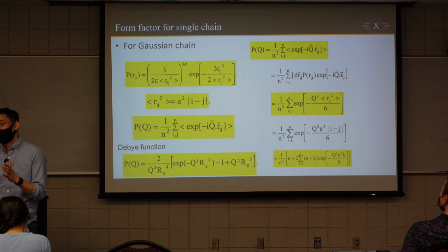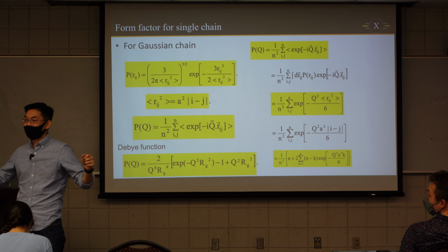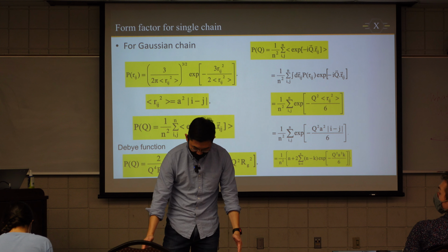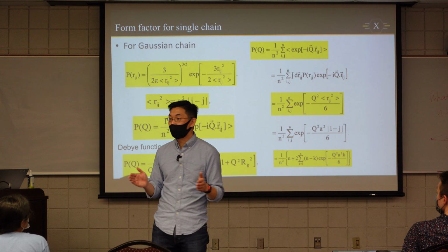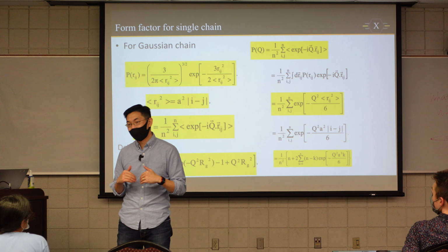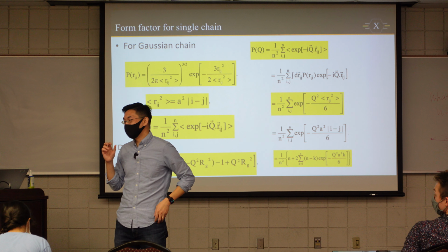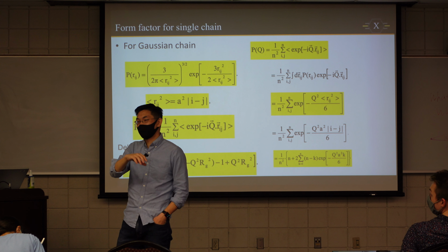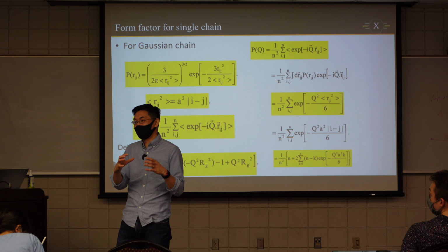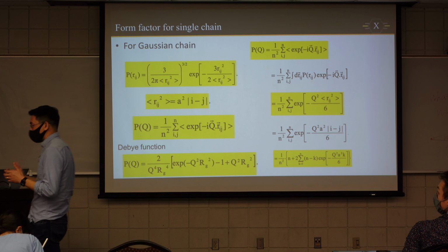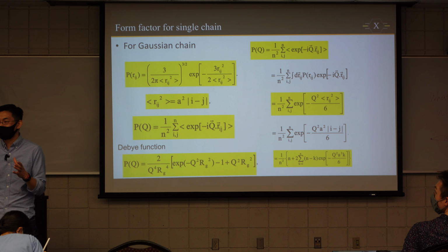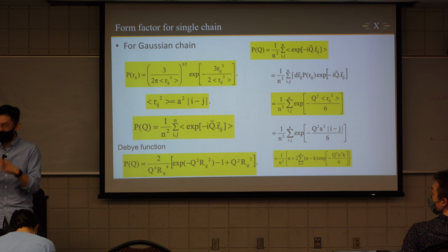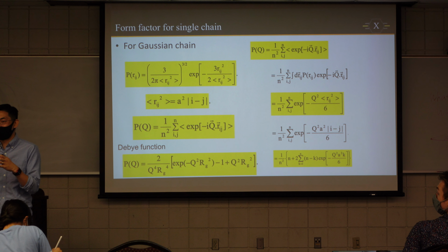At low Q, as I mentioned, our ruler is bigger. I think I didn't explain that one. With the bigger ruler, a consequence is that your measurement resolution also goes down at low Q. A good example is what you mentioned: a porous nanoparticle in polystyrene versus a gold nanoparticle, which is solid in the polymer matrix, assuming they both are 100 nanometers. At high Q, again, the ruler lets you magnify and see the detail. You will tell the difference between the porous particle and the gold nanoparticle.